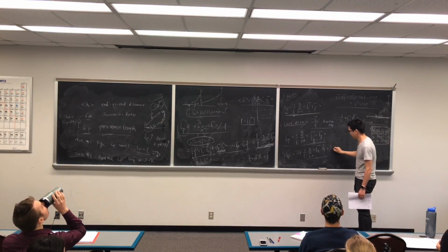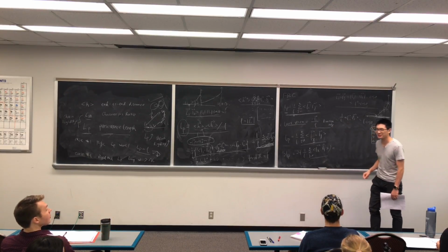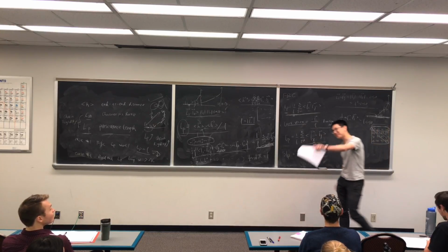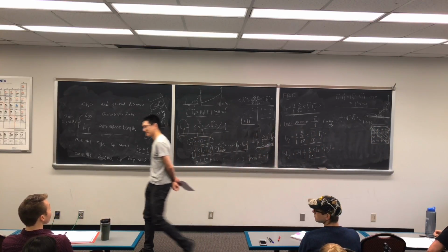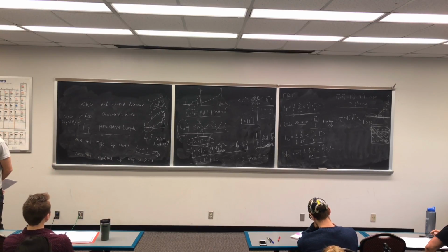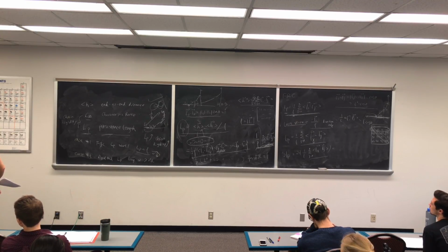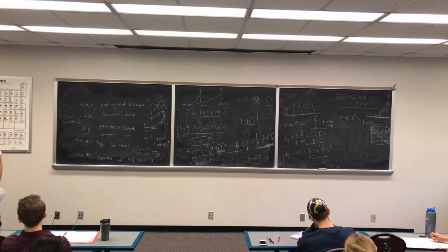Now, I think you guys have had enough equations. I'll just spell out the answer to you. A question again in the back? I may have missed this, but are we applying like a model to this, like FJC or? No, there's no model. It's a generalized. It definitely is not the free joint model, because what we did at the beginning of this class is talk about the free joint model. If it's FJC, the persistence length is just going to be L. It takes literally one bond to bend at 90 degrees, right?